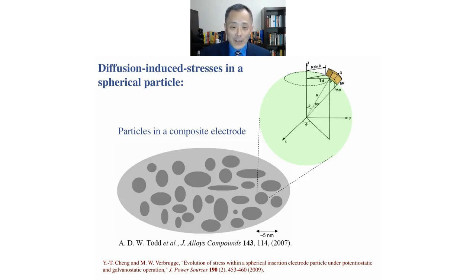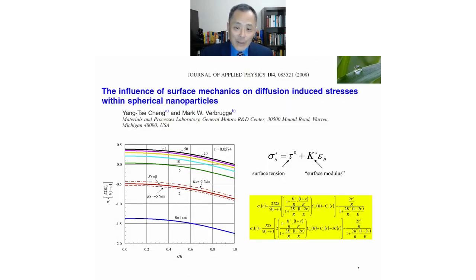Typically, commercial batteries consist of active materials in the form of particles, mechanically connected by polymeric binder, and electronically connected by carbon black in a composite electrode configuration. And some time ago, we did a study of diffusion-induced stresses in spherical particles. Our model took into consideration the effect of surface tension and surface elasticity, and showed that as the size of the particle decreases, the particles are less likely to crack.